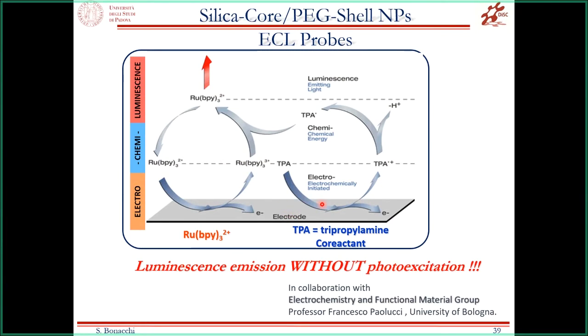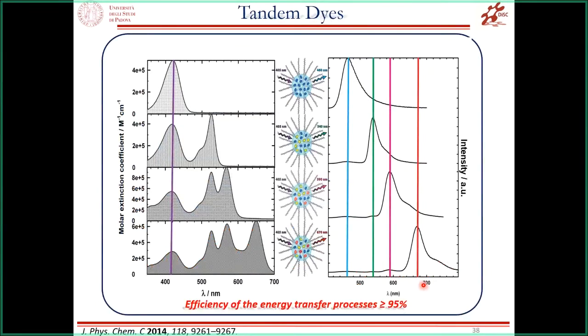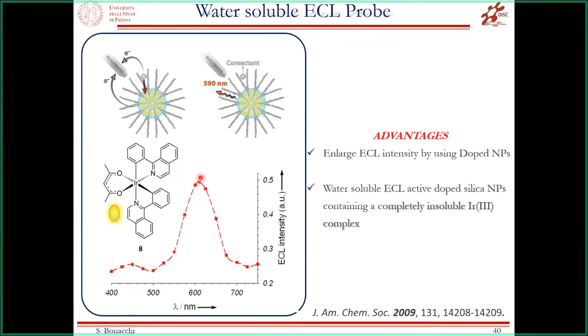So we use the same kind of approach with our dye-doped silica nanoparticle in order to again have fluorescence emission without photoexcitation, and so to increase the performance of this kind of silica nanoparticle. And this was one of our first achievements, in which we doped our dye-doped silica nanoparticle with an iridium complex. It's one of the well-known ECL active probes for this kind of approach.